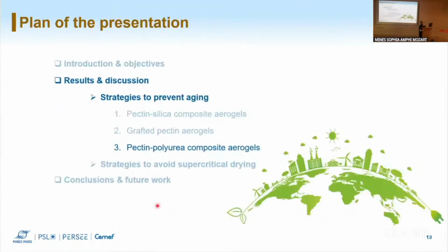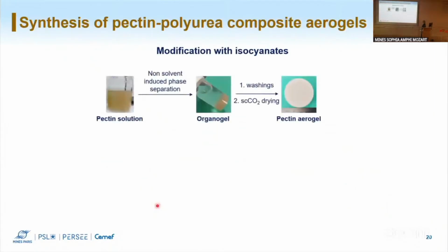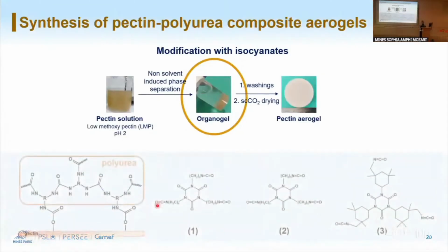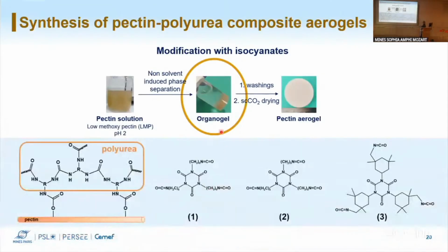Next, the last strategy to prevent aging was to prepare pectin polyurea composite aerogels. In that case, we did modification with isocyanates, and we worked with organogel again as a heterogeneous modification. For this work, we used the low methoxypectin at pH 2. Here we see that we used 3 different triisocyanate molecules that can be grafted on the pectin fibrils and then polymerized to create a polyurea network.